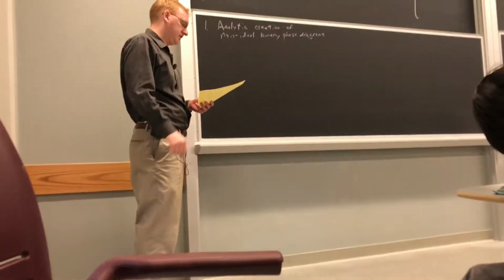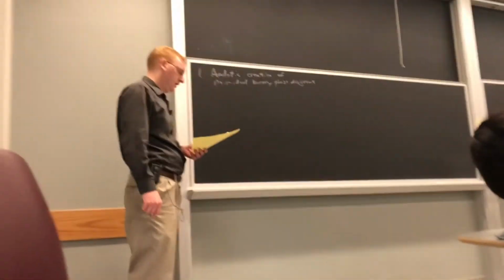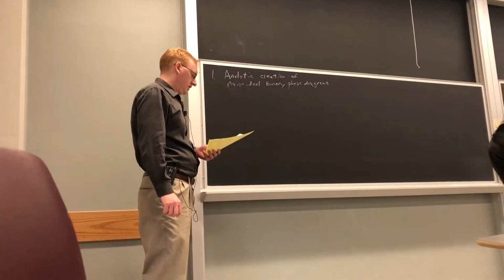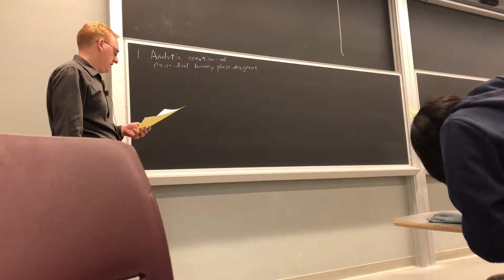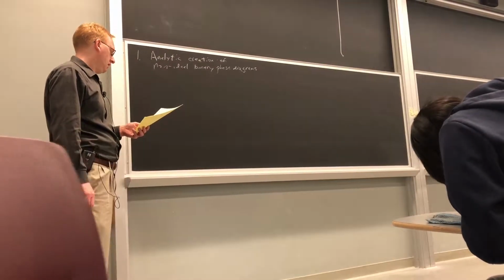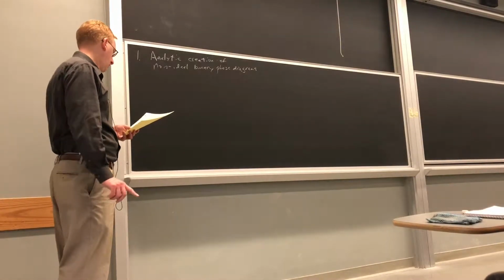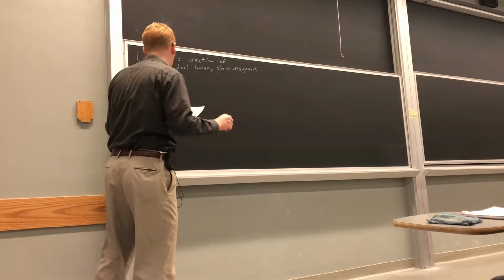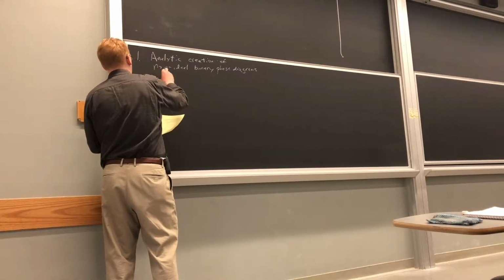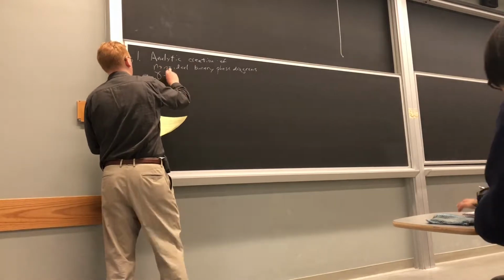How do we do that? If we're concerned about the liquidus and solidus, then one way to deal with it is to derive formulas from mu2 equals mu1, the equality of the chemical potentials, that are similar to the ones that we derived before and are in Olander as equation 8.11, A and B, and which I think you may have derived in homework, but in which we don't assume that gamma i equals 1. So we'll say with the gamma model.